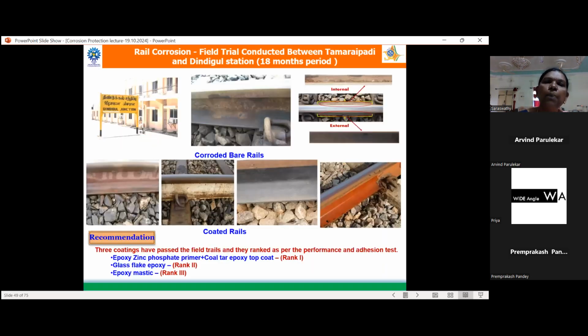So this is another important project which we have carried out for the RDSO. Normally during the morning hours, due to the excreta and urinals, the rails are getting corroded. So for that, they wanted us to develop a coating, and we have developed 3 types of coating, and we have tested in the rail over a period of 1.5 years, and we found that the epoxy zinc phosphate primer and coal tar epoxy top coat is performing better, and we have handed over this system to the RDSO.